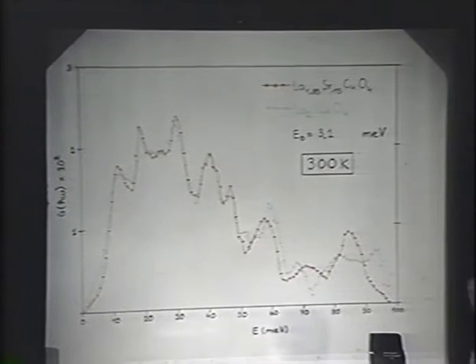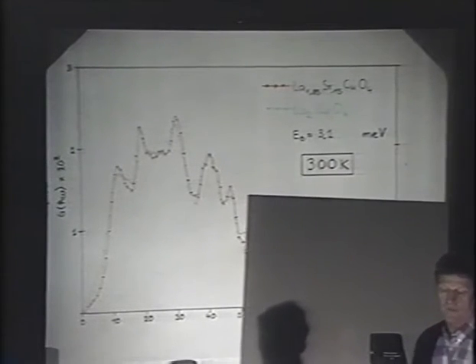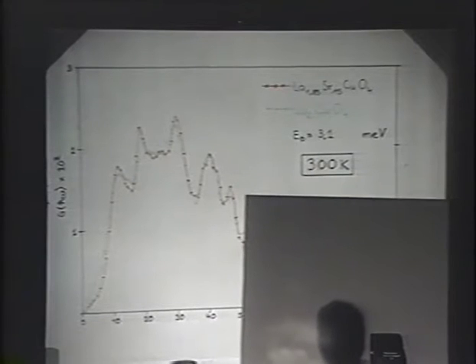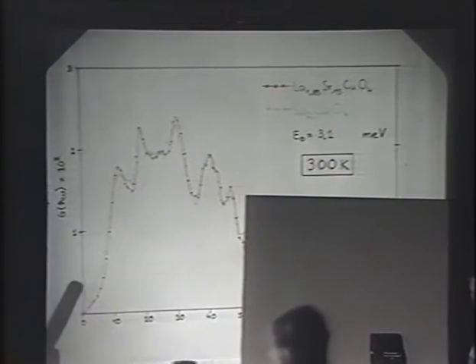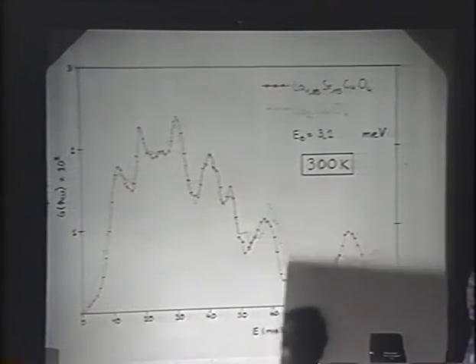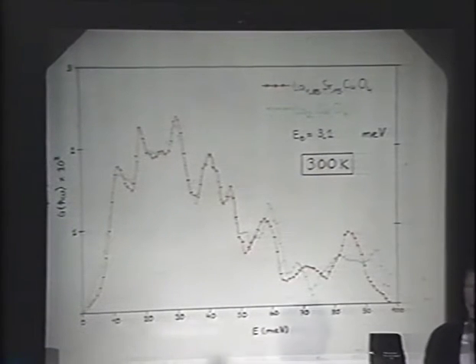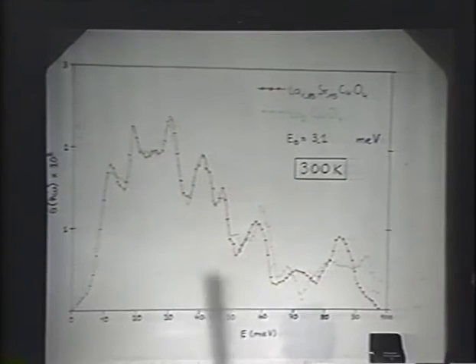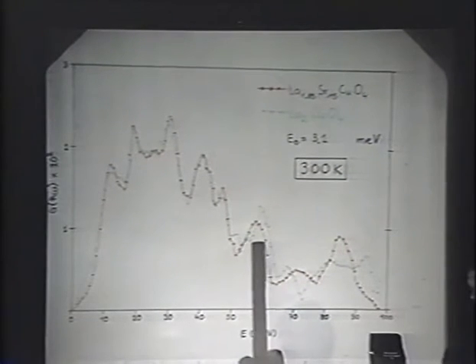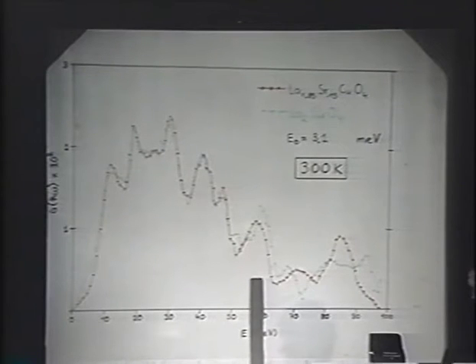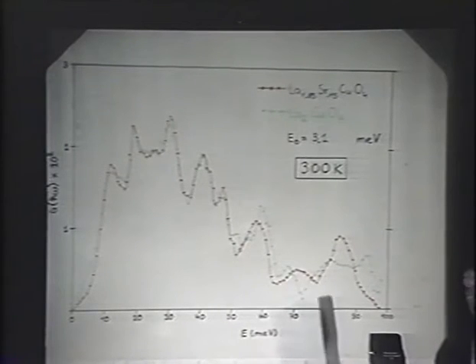What we see, maybe we look at the lower part of the spectrum first. Overall, very much alike. Here at low frequencies, at first astonishing that the non-superconductor seems to be softer, but it's understandable with the tilted octahedra giving rise to such bends, to such rotations or modes. In the upper part, here now we see a shift of these vibrations, whilst here the statistics were very bad on the second run.